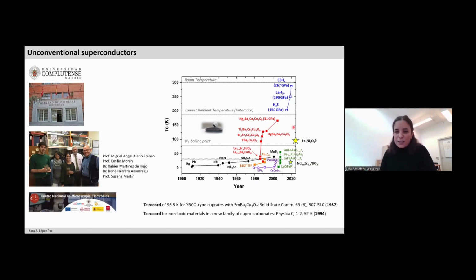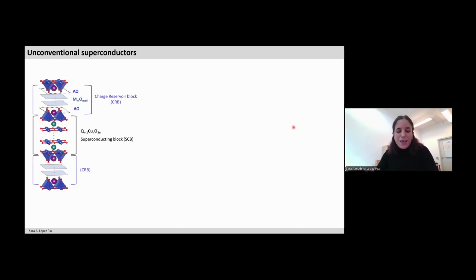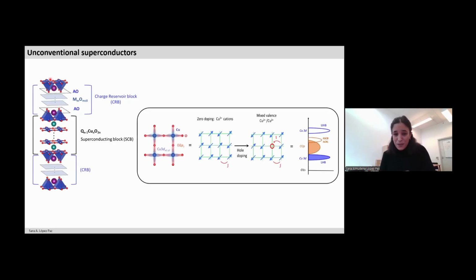And maybe to put it a bit into context, what was my problematic at the time: cuprate superconductors have very complex, layered crystal structures. But if we look at this system with a physicist mindset, we can simplify the problem and focus only on the superconducting planes, these copper-oxygen planes, and assume that the rest of the structure will just be a charge reservoir that will supply some holes for conduction. In this way, the problem is reduced to a very simplistic toy model where we have just a square net of copper spins which are localized and antiferromagnetically coupled. And superconductivity will emerge when we introduce some holes for conduction into these planes.